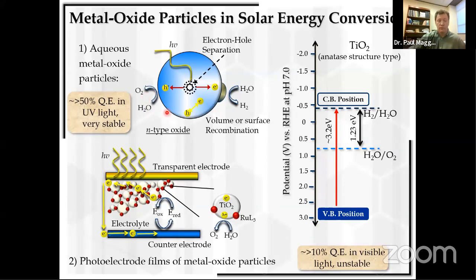And so what you do is you take these particles, and rather than just dispersing them into an aqueous solution, you deposit and anneal them as a film, typically on something like FTO or some sort of transparent conducting oxide. And then in order to facilitate visible light absorption, little dyes are put onto the surface. And then those little molecular dyes can inject electrons and or holes into that film, which finds their way to the other electrode. And so on one electrode, you can drive water oxidation, and on the other electrode, you can drive water reduction. And this can be some reversible redox couple where what you're doing is you're generating electrical power, or you can be driving 2 redox couples that generates fuel, such as, again, water reduction and water oxidation.